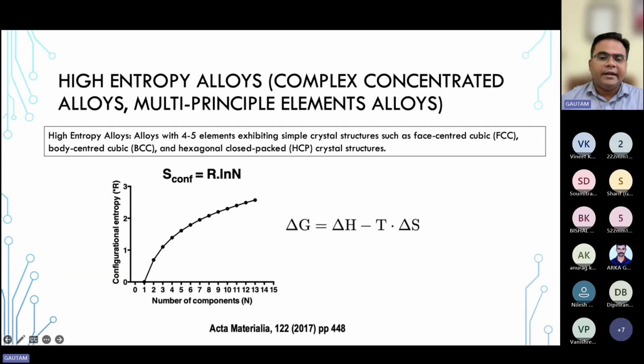So that was the initial hypothesis about the solid solution stabilization in these kinds of systems. The idea was very simple: we know that the Gibbs free energy change, delta G, is written as delta H minus T delta S. Delta H is the enthalpy change associated with the mixing, T is the temperature, and delta S is the entropy. Initially, the hypothesis was that delta S increases significantly as the number of components in the system increases. This is how delta G goes negative when we have a large number of elements, and this is how the entropic stabilization takes place.